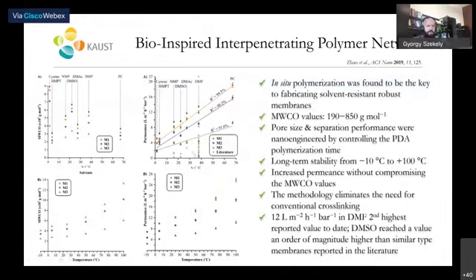And here you can see the results. So we tested these membranes again to confirm whether they are able to separate A and B. So this is about the selectivity, and then we looked at the permeance, the throughput of the membrane. And here we managed to find literature data that is represented in gray asterisks. What you can see here is that the higher the permeance, the better. So you can see that all of our membranes, 1, 2, and 3, perform quite well compared to the literature. And there was only one membrane that had outstanding performance in the literature, way better than any other literature values or our values. We also investigated the effect of temperature that you can see here in these two graphs.